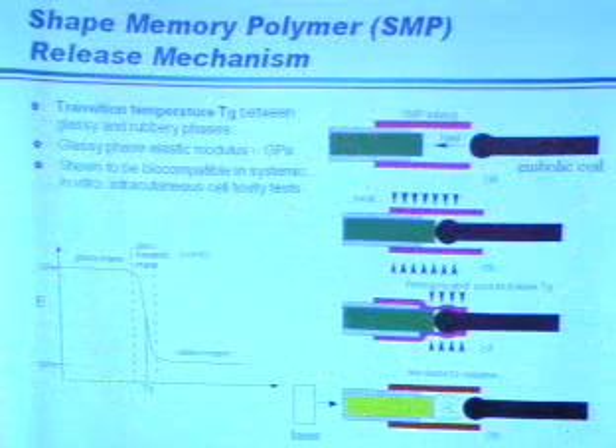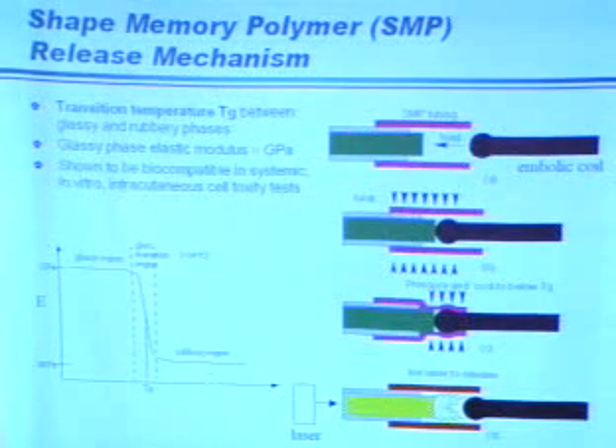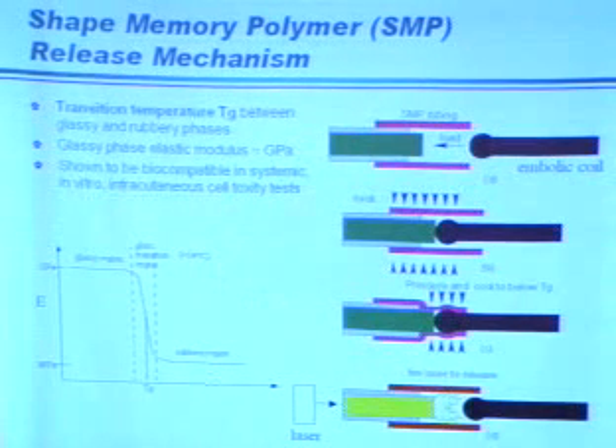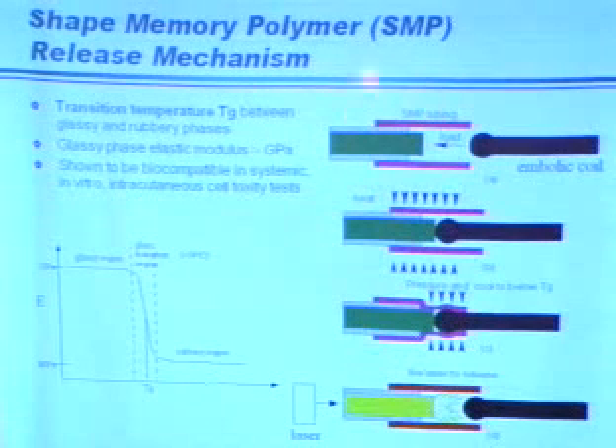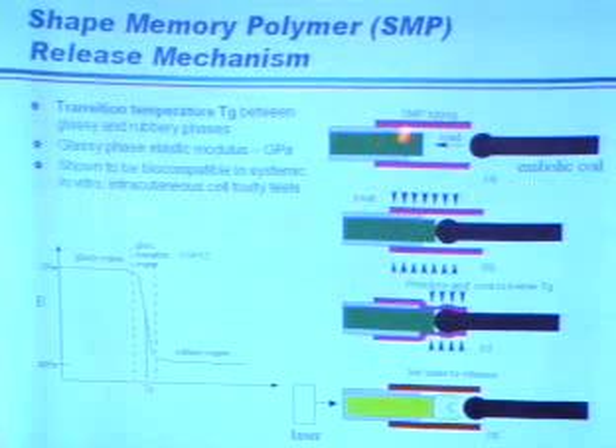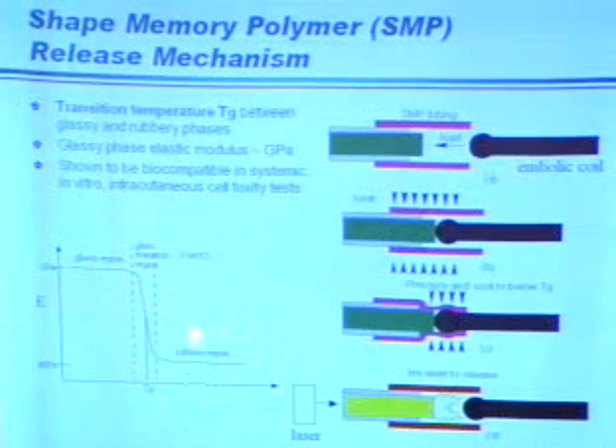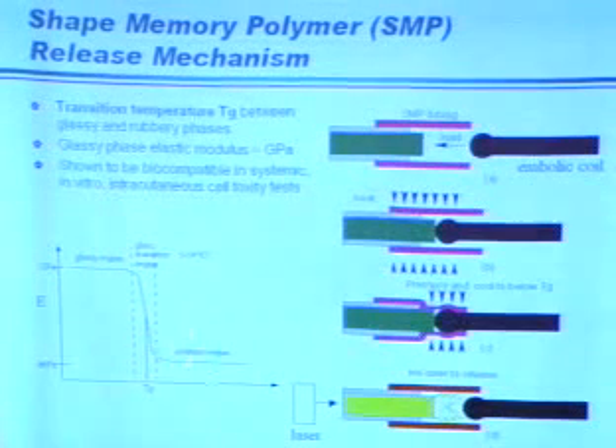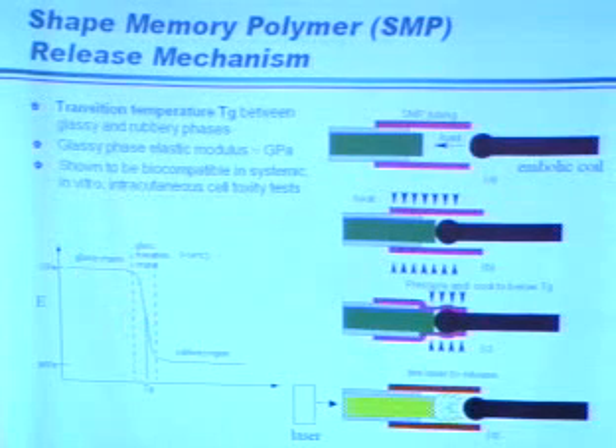We had another trick up our sleeves at that time, which was not quite a MEMS solution. So it tells you that the main thing is to solve the problem at hand. We used another shape memory phase transformation material, which is a polymer instead. This polymer has a different kind of phase transformation. At the high temperature phase, which is the rubbery region, it's only megapascals. It's very, very soft. Whereas in the glassy region at lower temperature, it's very stiff. It's like Kapton. It's really, really stiff. So it's about a 400 times change in the stiffness.